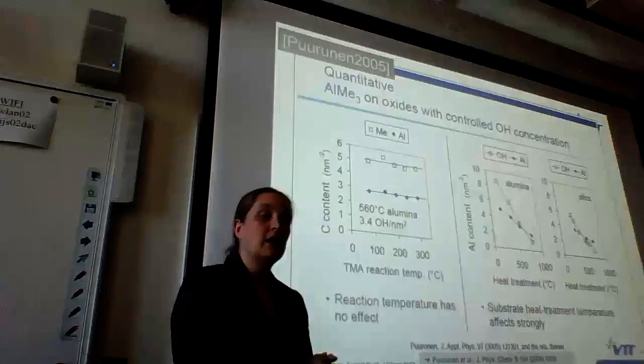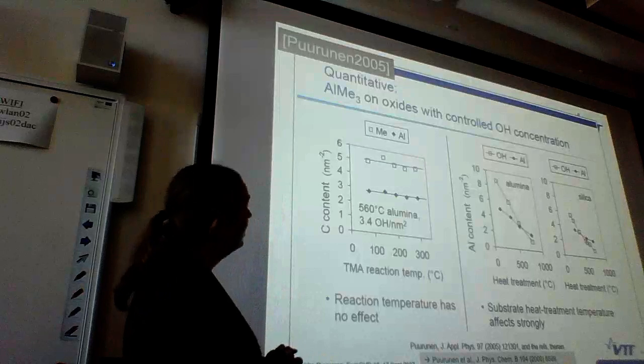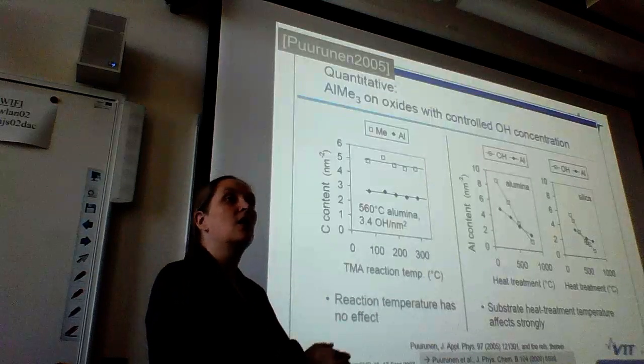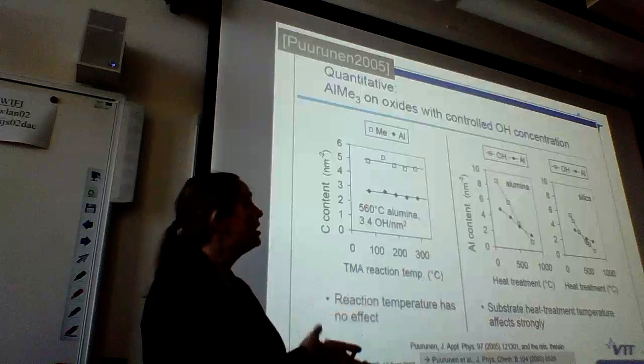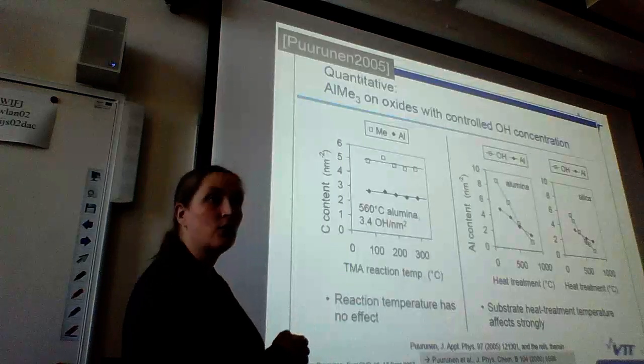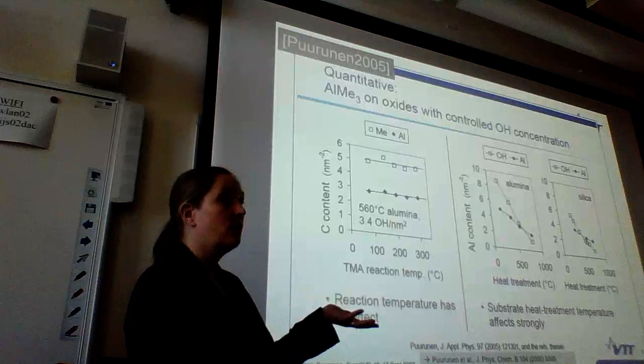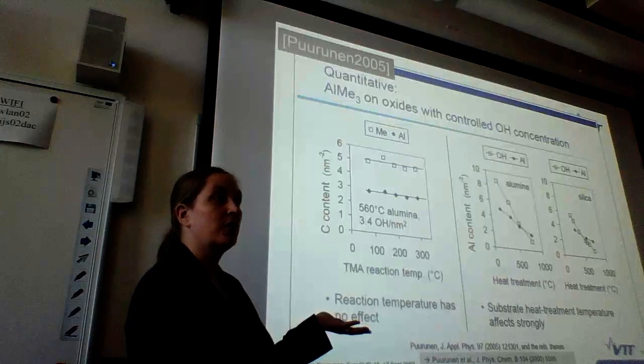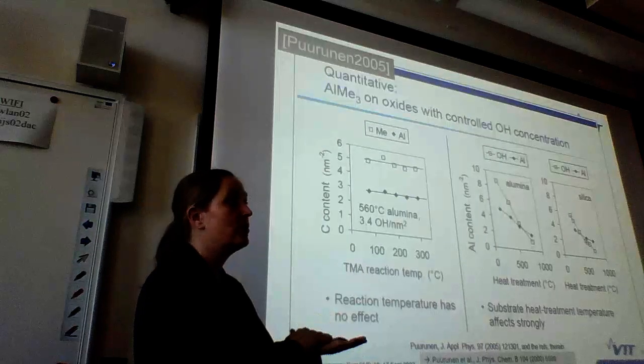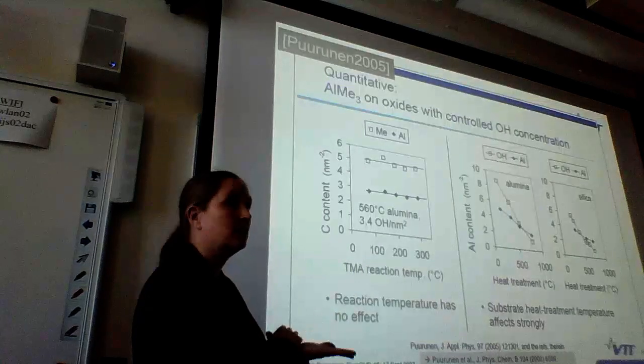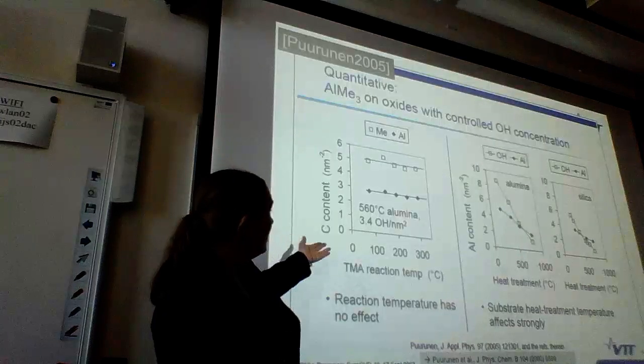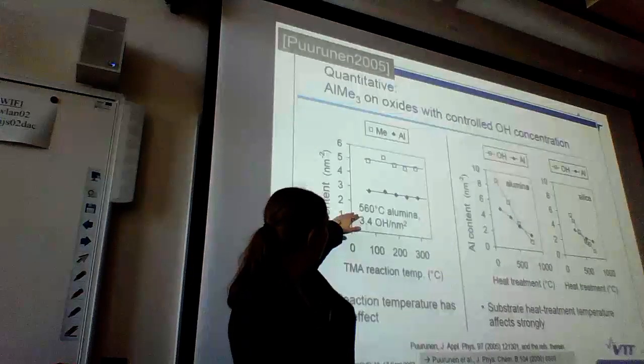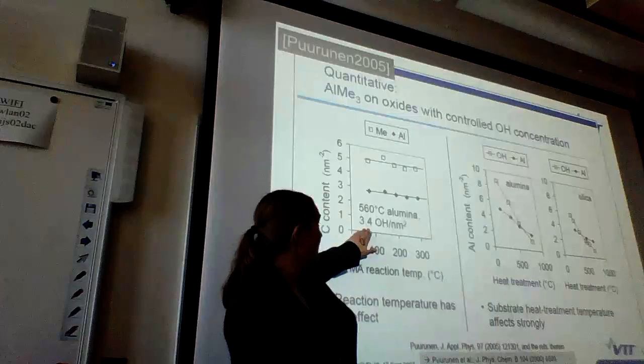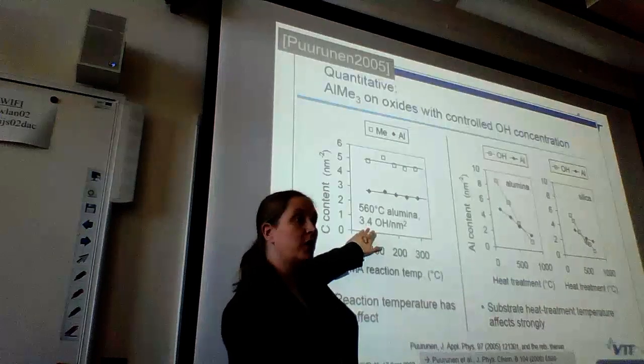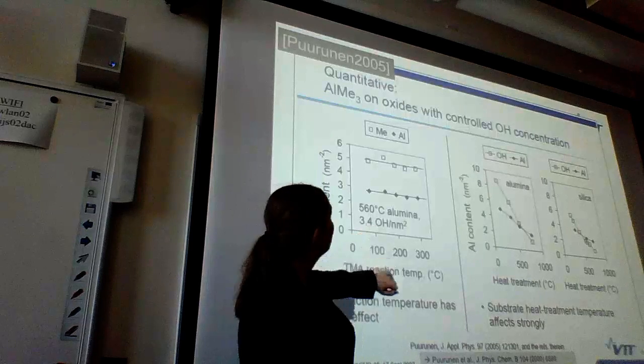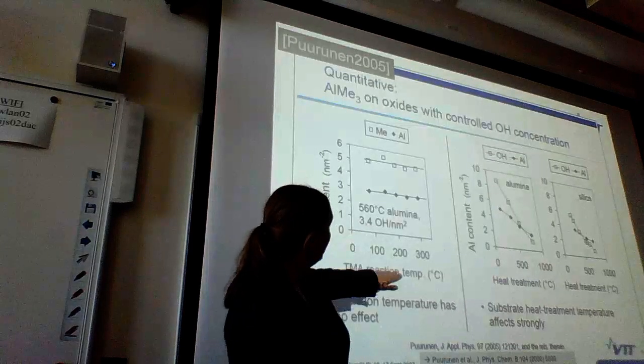But this is what I did actually in my doctoral studies. I was investigating this exact reaction on porous oxides, high surface area, alumina and silica. And the great thing in those is that you can actually control and measure the OH group concentration. You have such a high surface area that you can use totally different analysis techniques as you can for silicon wafers. So we prepared aluminium oxide heated at 560 degrees centigrade that had 3.4 OH groups per square nanometer measured by hydrogen NMR. And this, you react with TMA at different temperatures.